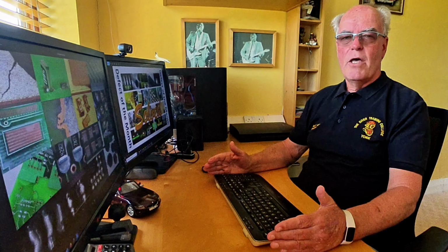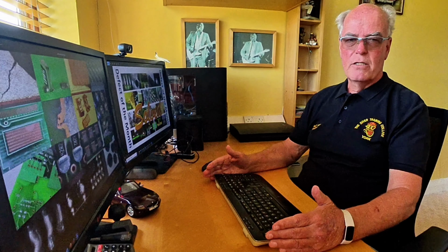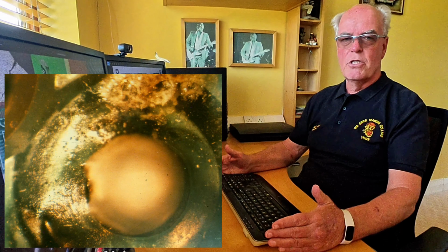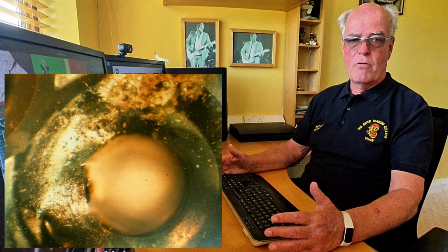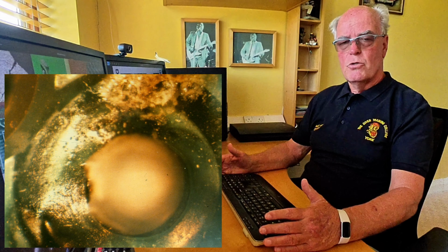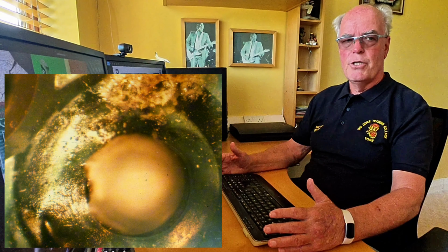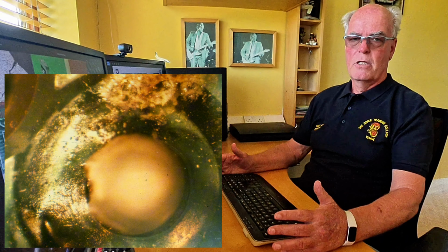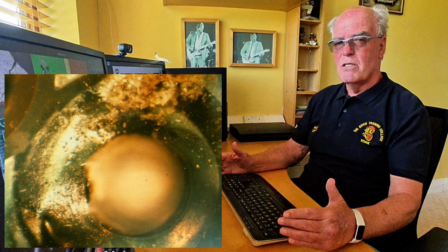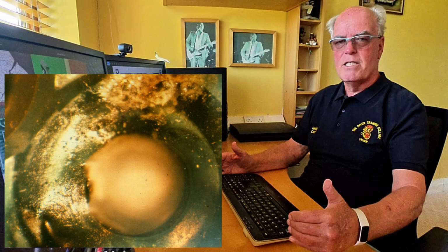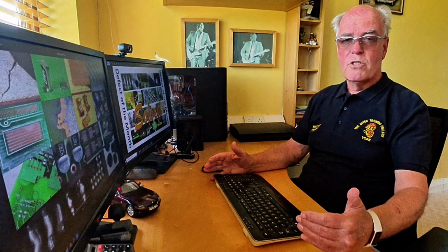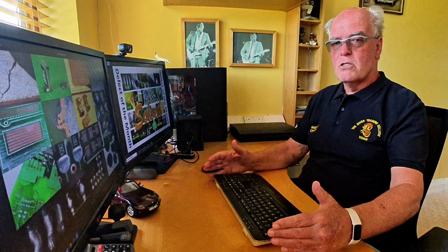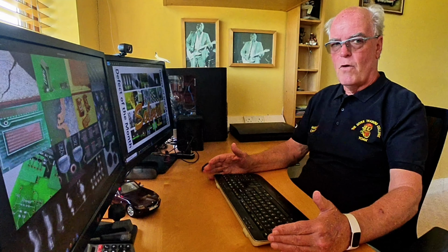The very first time I ever experienced dendrite failures was on a product which was in operation only for a few days, but in a very hostile environment. This image shows how corrosion has occurred underneath the solder mask. Now, this really was poor design. The solder mask has been defined right up to the pin, and this pin was soldered using wave soldering in the process using a water-soluble flux.